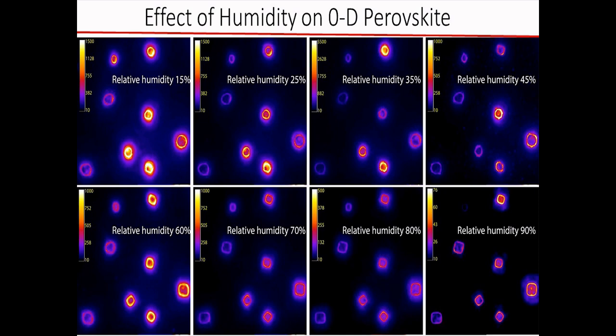When we increase the humidity on these particles, you can see that around 60% humidity, the particles started to change their shape from round to a cubic form, the square shaped particles. This is a 2-dimensional projection, so that's why you see it as a square, but in principle these are converting into cubic shaped particles. The intensity also gradually reduced when we increase the humidity.